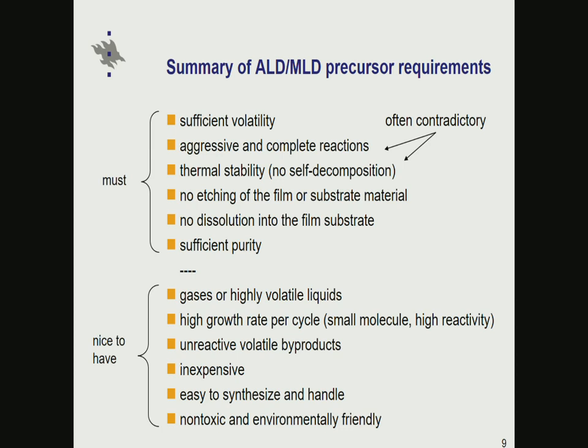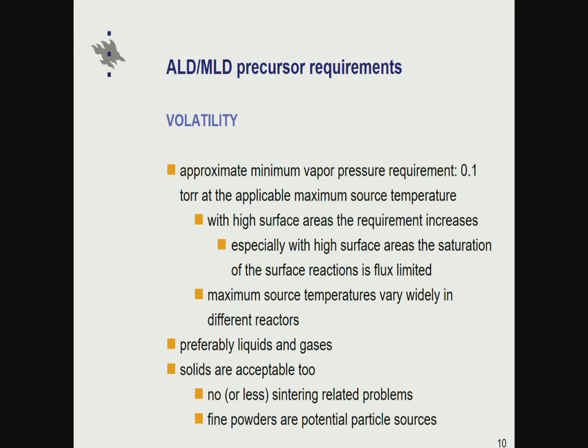Now I will go through these one by one and open them up a little bit further. Volatility is quite obvious. ALD is a vapor phase technique, so to bring the precursors over the substrate surface, we need to transfer them into the vapor phase. What is volatile enough? That's a trickier question, but roughly speaking it should be something like 0.1 torr or 0.1 millibar at the applicable maximum source temperature, which of course depends on the reactor you are using. I will show examples of that in the next slides.